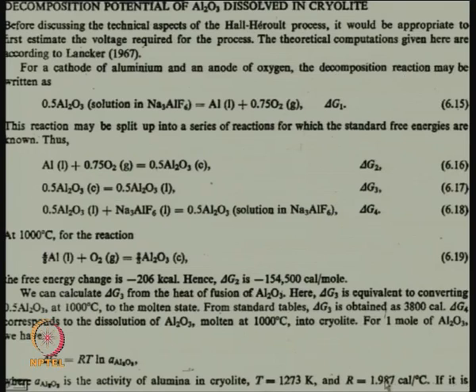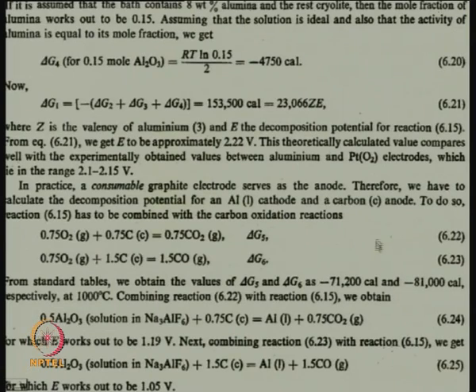Temperature is this, R is this. If it is assumed that the bath contains 8% alumina and the rest cryolite, then the mole fraction of alumina works out to be 0.15. If you take the molecular weight, mole fraction is 0.15. Assuming that the solution is ideal and also that the activity of alumina is equal to its mole fraction, we get delta G4 equal to RT ln of this. So, now you add up all this to get the final value, and that is equal to Faraday constant times Z, which is 3 valency, into E.